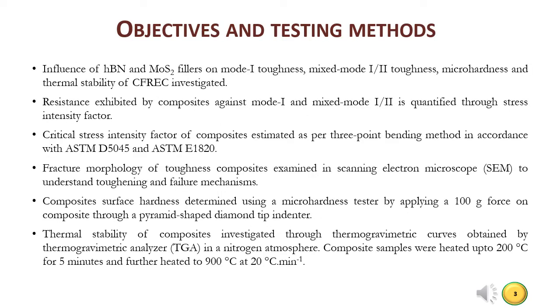Hexagonal boron nitride and molybdenum disulfide are the two fillers selected in this study. The influence of hBN and MoS2 on pure mode 1 toughness and mixed mode 1 and 2 toughness, microhardness and thermal stability of CFREC is investigated. The resistance exhibited by the composite in crack opening tensile and combination of tensile shear modes is quantified through critical stress intensity factor as per ASTM D5045 and E1820 standard. Fracture morphology of toughened composites is examined using scanning electron microscope to understand toughening and failure mechanism. Temperature withstanding ability is investigated through thermogravimetric analyzer in a nitrogen environment.